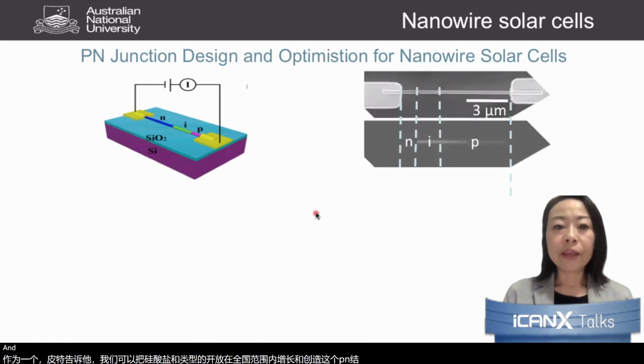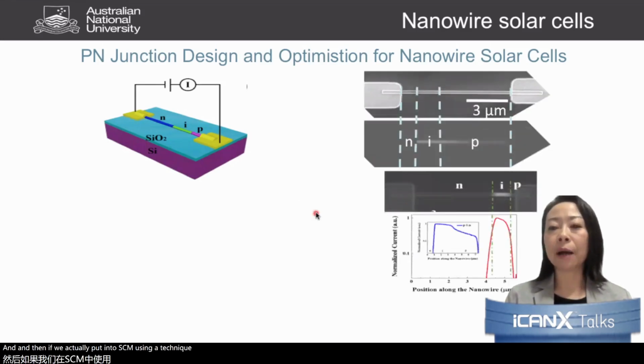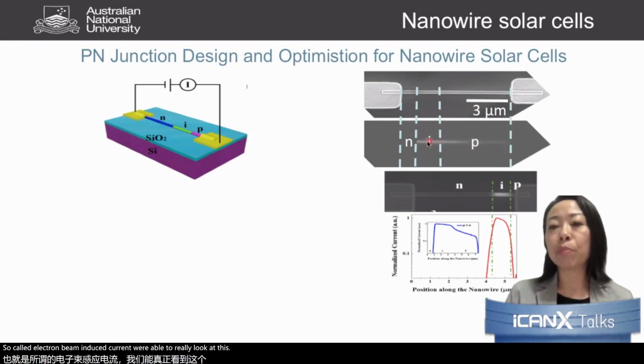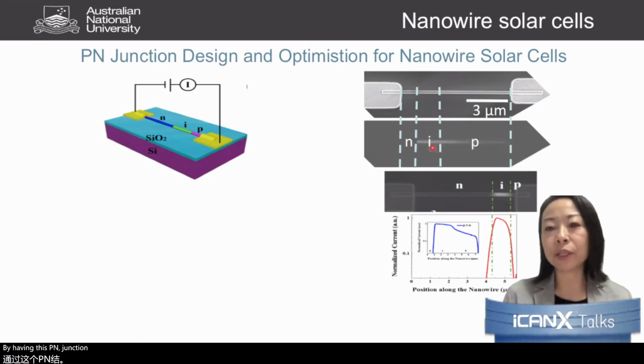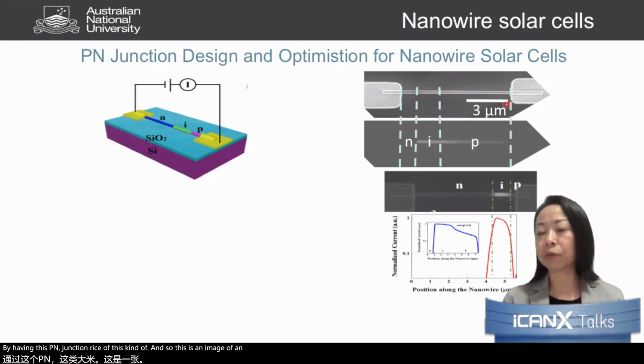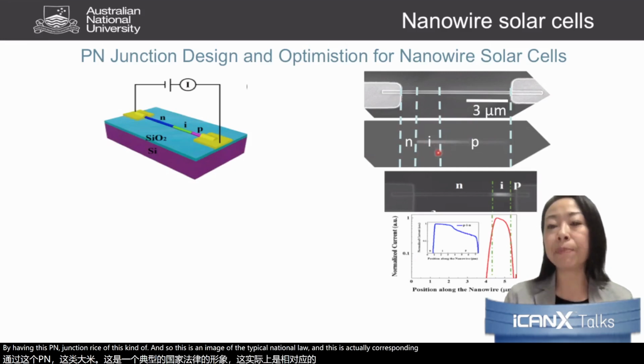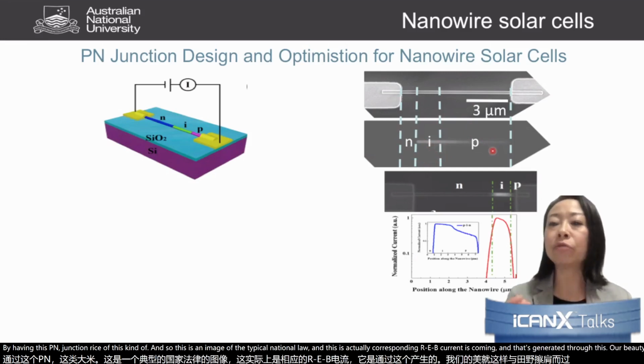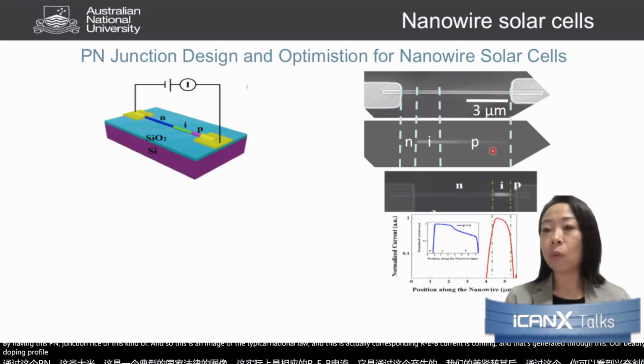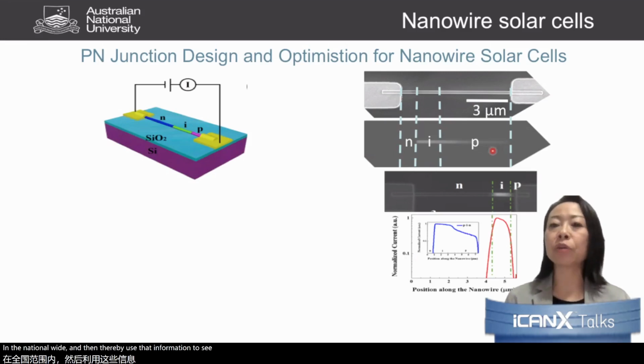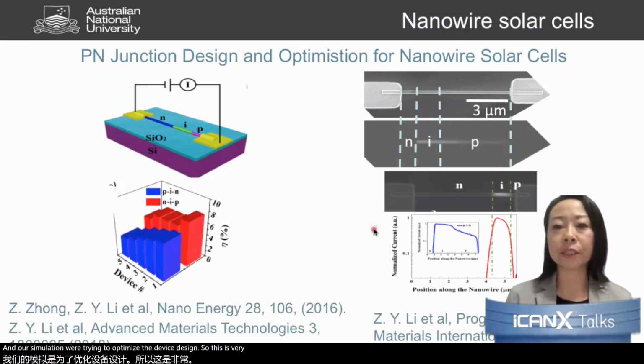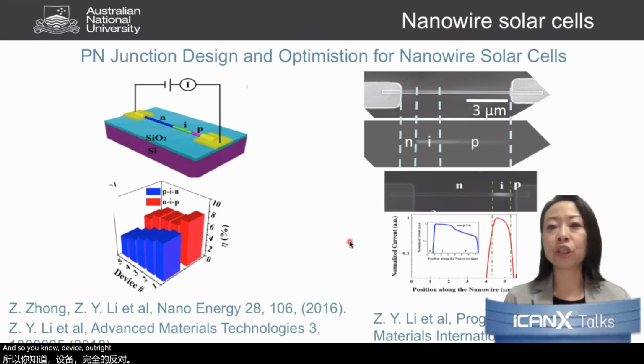And then if we put it into an SEM using a technique called electron beam induced current, we are able to look at the profile of the built-in electric field formed by this PN junction, right? So this is an SEM image of a typical nanowire, and this is the corresponding EBIC current that is generated through this built-in electric field. Through this, you can look at the doping profile in the nanowire, and then use that information to feed back to the growth and our simulation to optimize the device design. So this is very important for device optimization, also for solar cell devices.